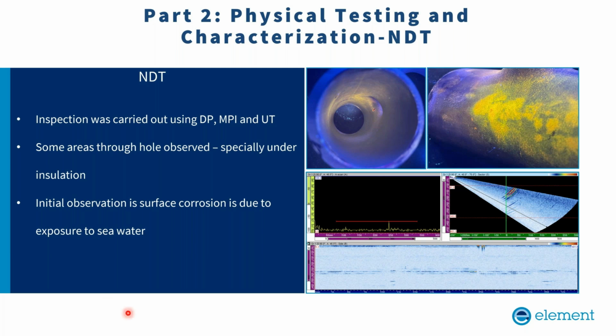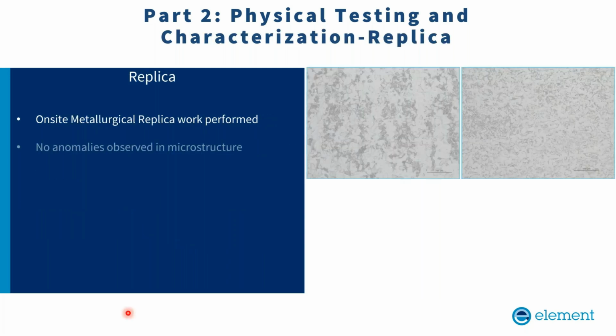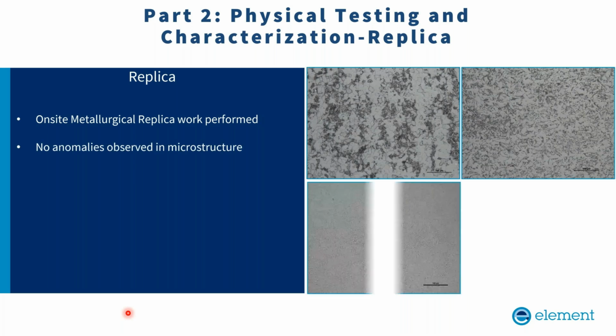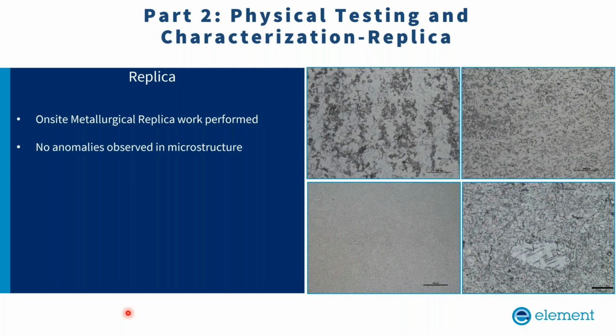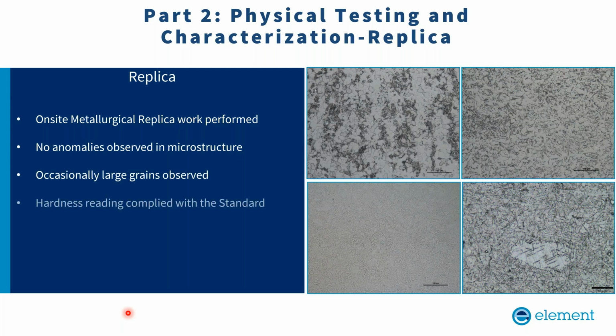To assess the condition of the asset, we have also done replica analysis in several locations of the pipe. We have mostly found the structure is as per the expected microstructure of the material. However, occasionally large grain size was found in some locations, as shown in the right bottom of the picture. However, these grains didn't contribute to any failure of the structure, and these were only occasionally found in one or two locations. A complete hardness test was done.